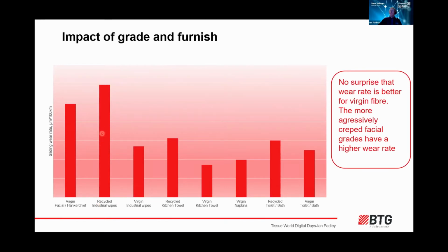Recycled industrial wipes have quite a high wear. Again, this is the nature of the furnish coming through, a higher ash content. Virgin kitchen towel, commonly running on a great big dollop of wet strength resin, which will stick to the Yankee as well, and creping at a higher moisture, fairly low wear. No real surprises there, but it's nice to see some of our thought processes validating the data here.